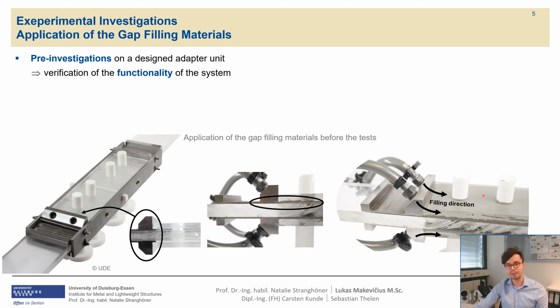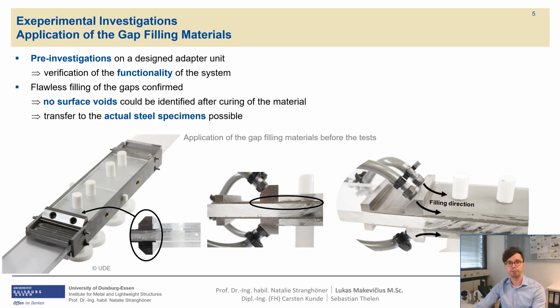Furthermore, special pins were created in order to guarantee a minimum clearance hole of 17.6 millimeters. The pre-investigations confirmed the flawless filling of the gaps. Also, no surface voids could be identified after the curing of the material, so that the same procedure, including of course the adapter units, was applied to the actual steel specimens for further testing.